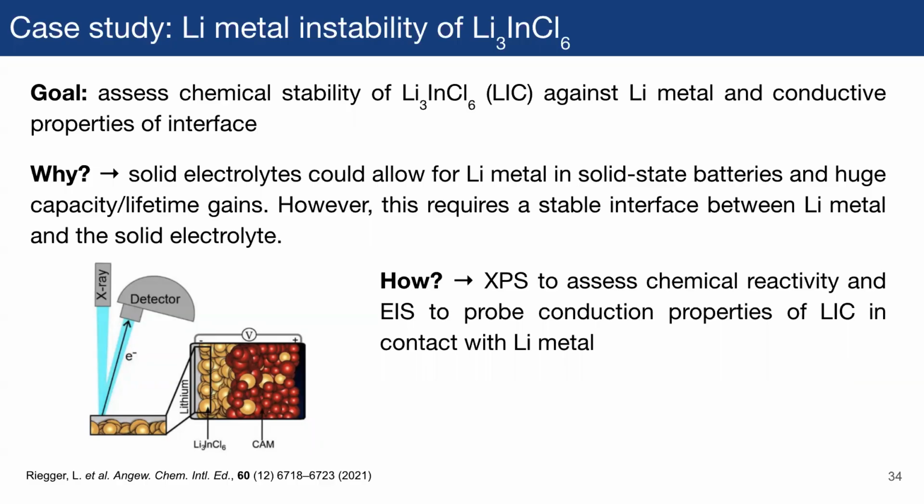The reason this kind of study is really interesting is because solid electrolytes are a way to potentially incorporate lithium metal into solid state batteries, which would allow for huge capacity and lifetime gains. The huge problem with that is that it requires a stable interface with lithium metal, and that is difficult to achieve.